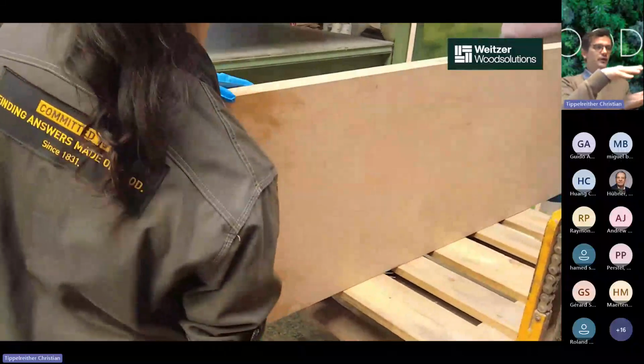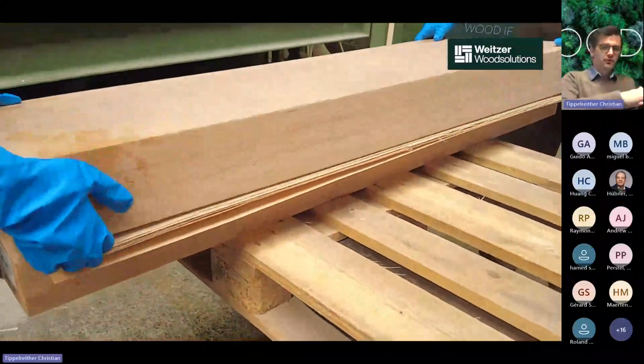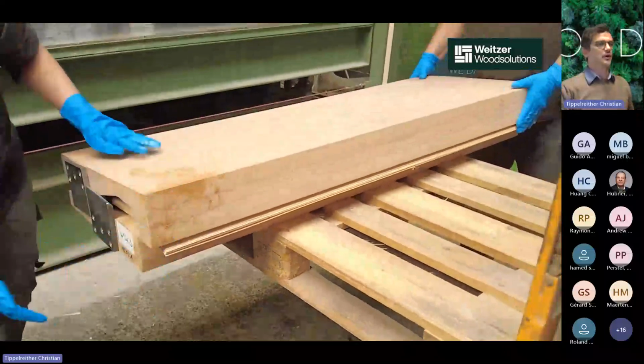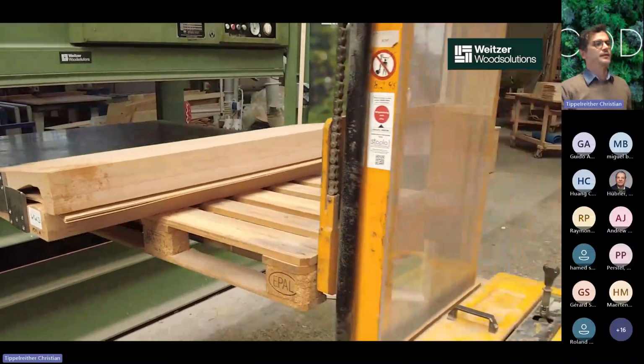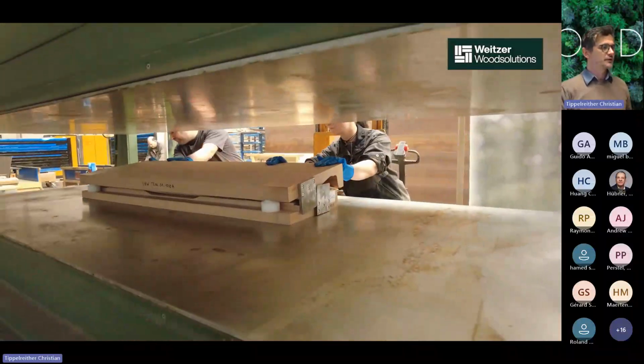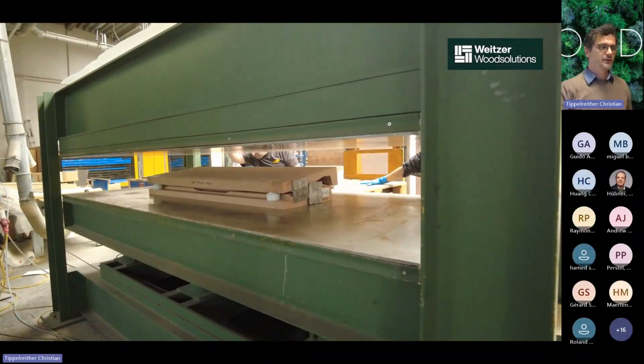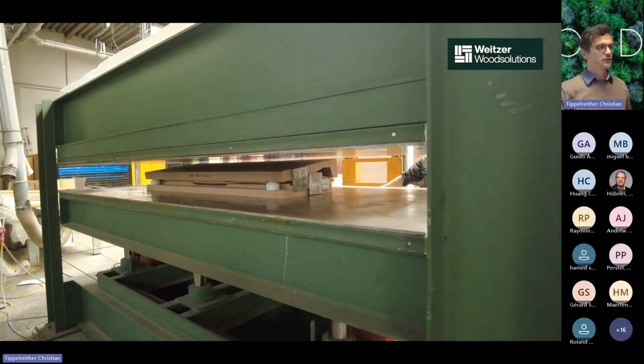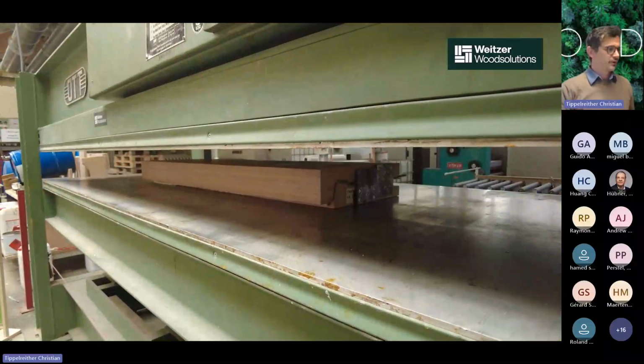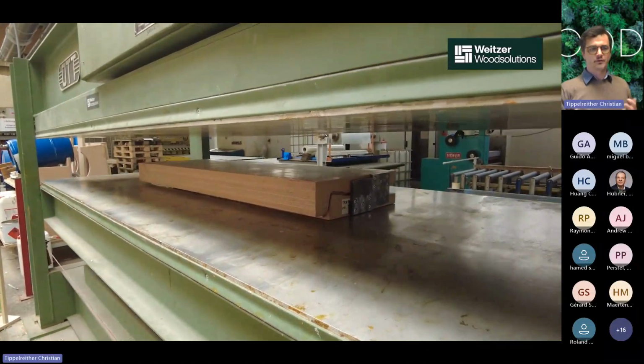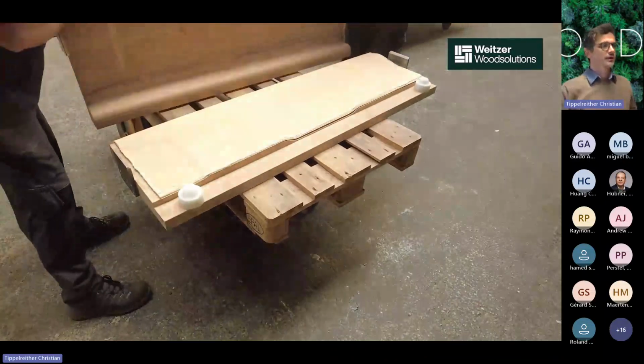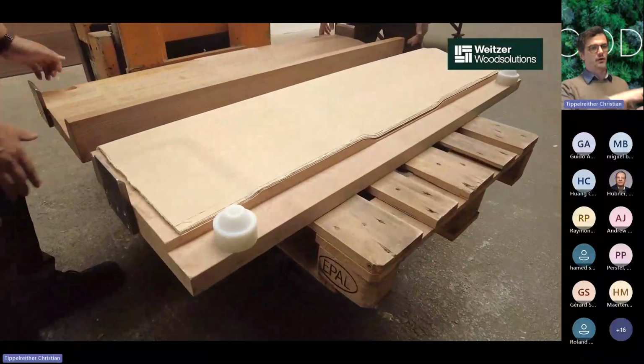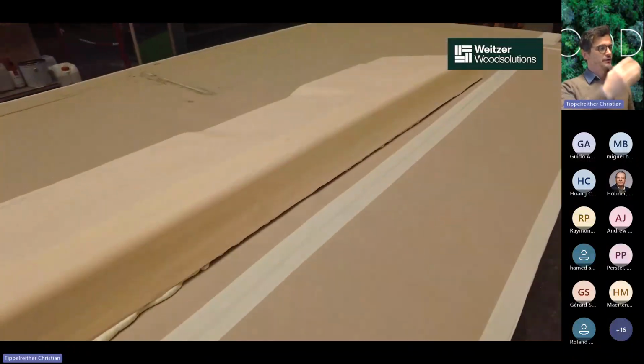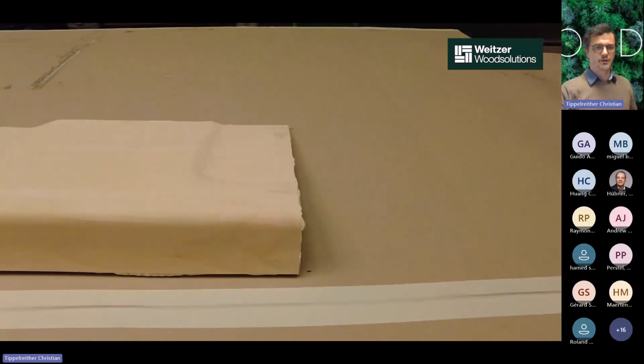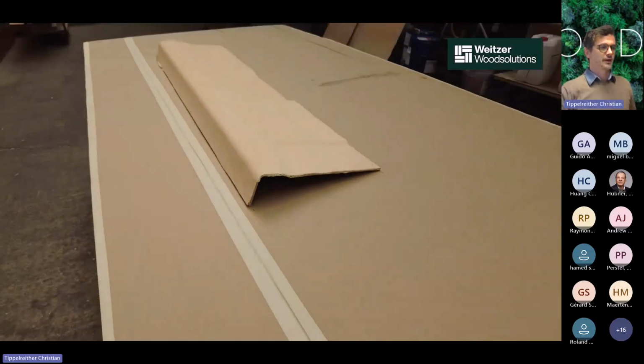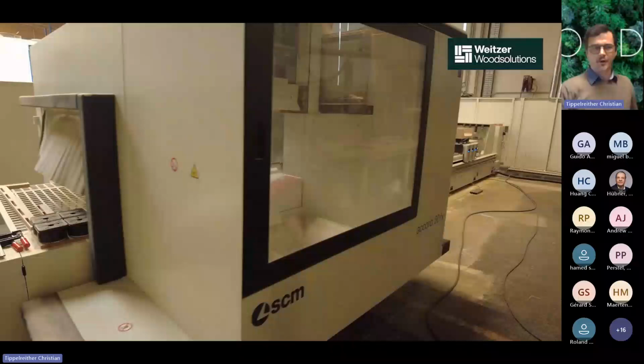You also have a different layup here, from 0, 90 or 45-degree layups with different prepreg stiffnesses, and that's the same here. Only with wooden veneer layers we use 1 millimeter in thickness or 1.5 millimeters, or if it's needed also thinner. Press it in a pressed mold. Depends, of course, on which glue you need, and then it's demolded, and then you have, as you see here, a complete pressed part in a 3D layer shape, as it is needed for our customer, for our purpose, and so on. Then it's quite similar to any other product.